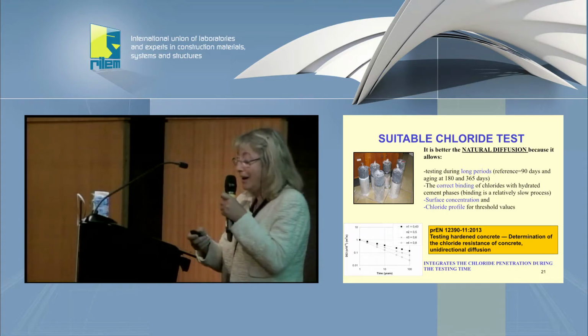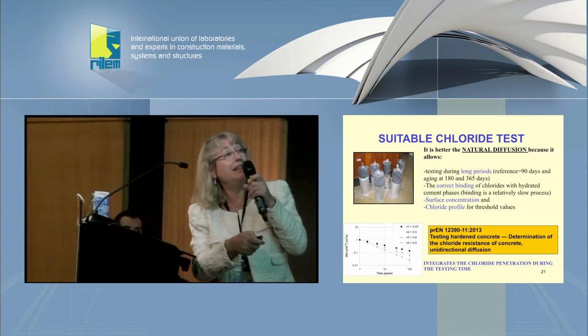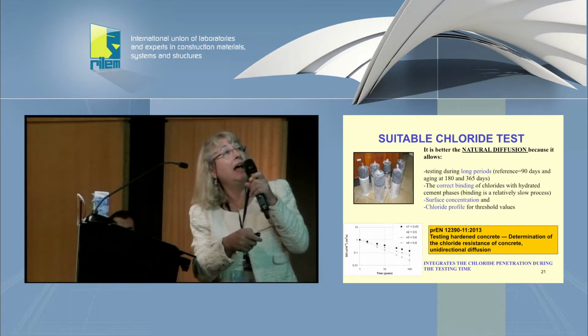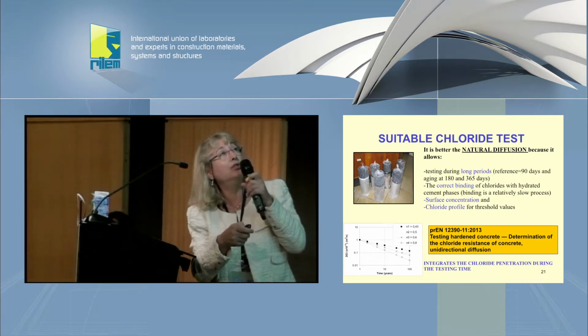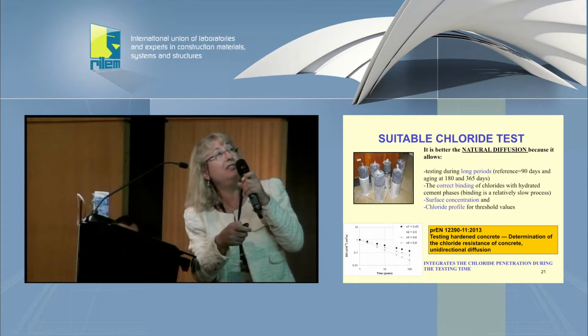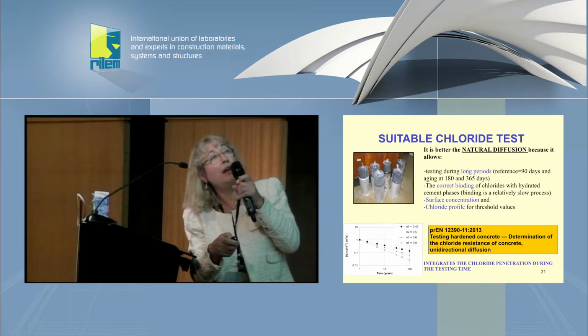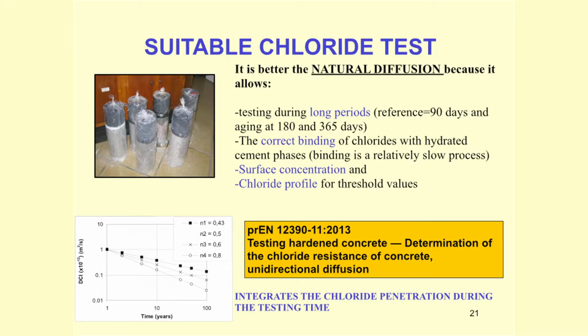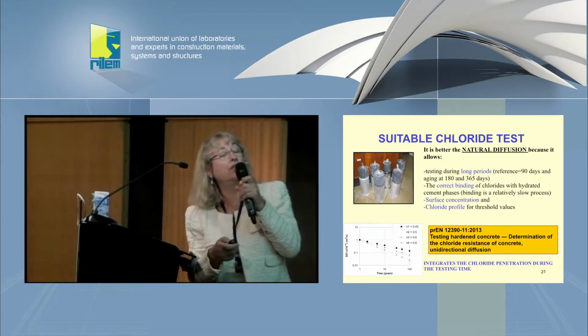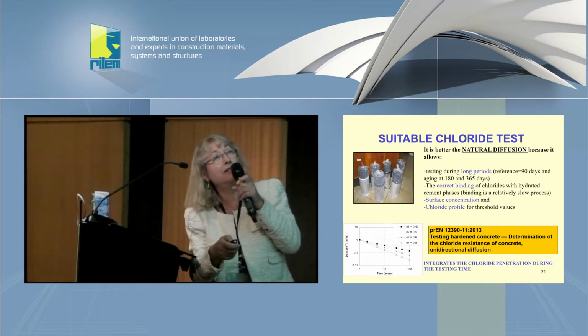It is an integral test in the sense that it gives the performance after the chloride has been acting continuously on the concrete. The concrete ages in the presence of the salt water, and it also allows a correct binding of chlorides. It is possible to obtain the surface concentration from the chloride profile and also the threshold value. In that case, I think it is the most suitable test for testing of the mixes, in spite that it takes a minimum of 90 days, or even longer for aging.